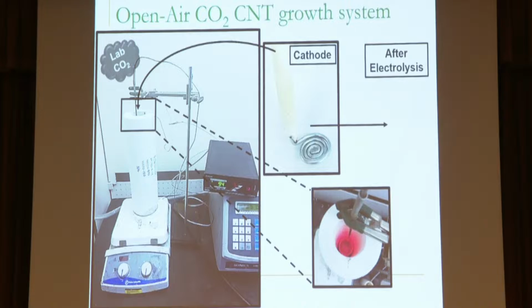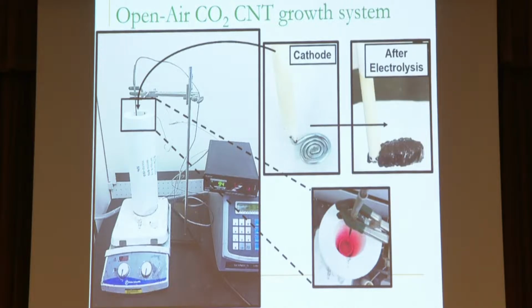Then we use electrochemistry. So we have a cathode where the carbon is deposited, and we also have an anode where oxygen evolves. And I'll explain the chemistry here in just a minute. But the way this works is we stick our electrodes in, we apply a voltage, lab air goes in to supply the carbonate with carbon dioxide, and we break the carbon from the carbonate and grow carbon materials and carbon nanotubes, and this is what we get after we go through this electrochemical process, right? So this is from carbon dioxide that comes directly from the air.